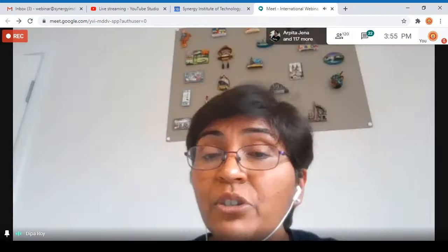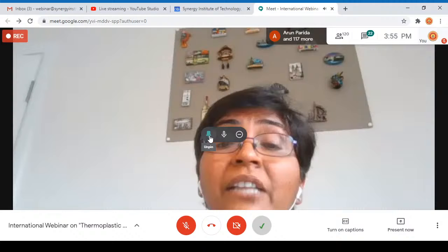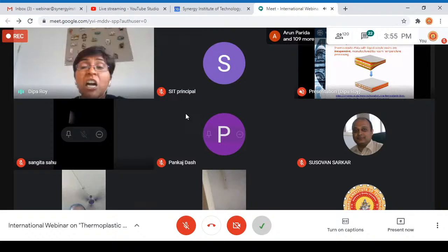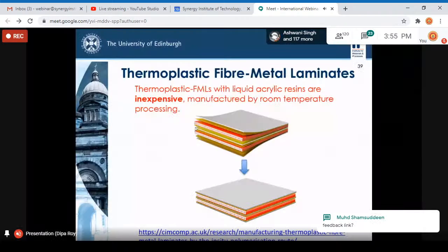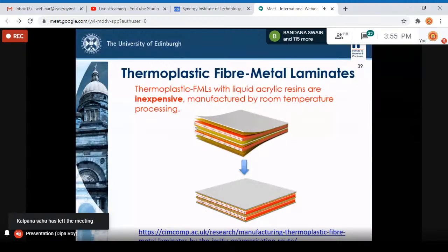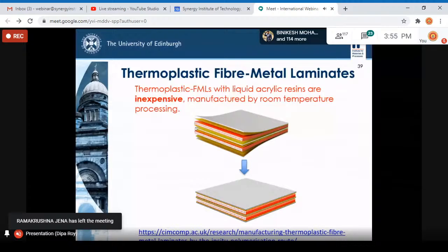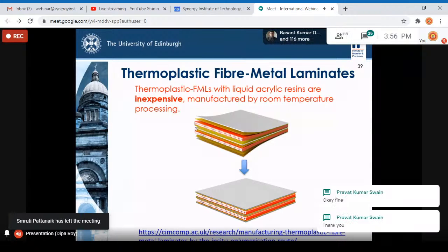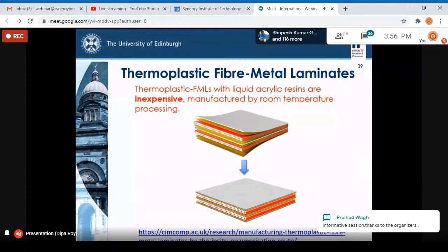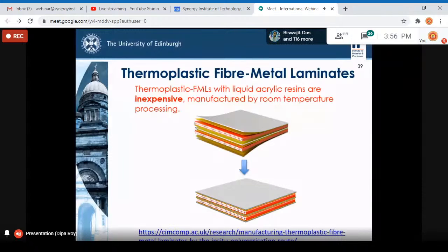room temperature. So if we can manufacture such hybrid laminates at room temperature, then we can avoid having those residual thermal stresses at the interface because the curing is not involving any high temperature. So in spite of having a mismatch in the thermal expansion coefficient of the composite layer and the metal layer, we can still manufacture effectively without adding those manufacturing stress factors. This work was actually funded by the EPSRC Future Composites Manufacturing Research Hub feasibility study, and we manufactured these thermoplastic fiber metal laminates successfully.